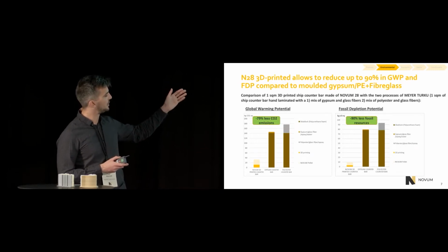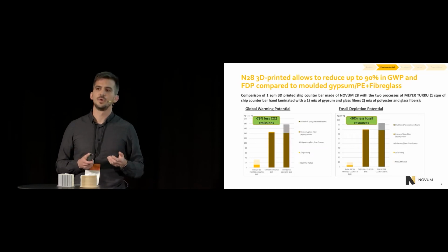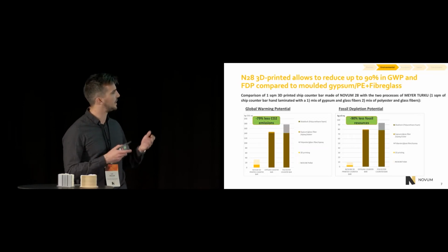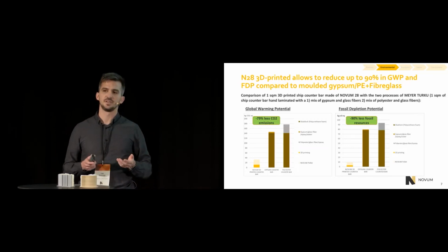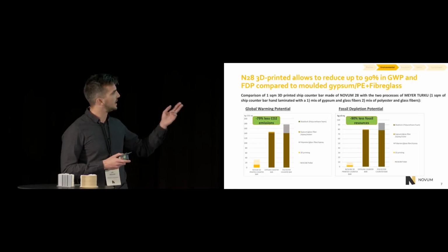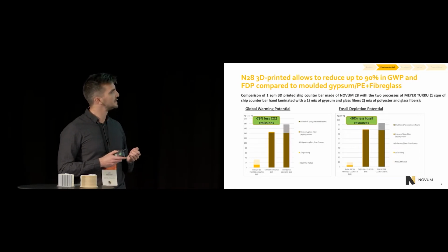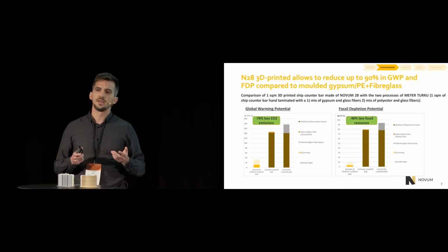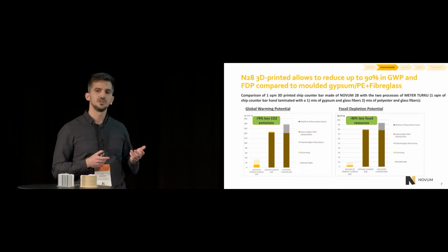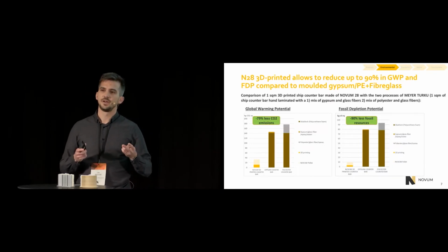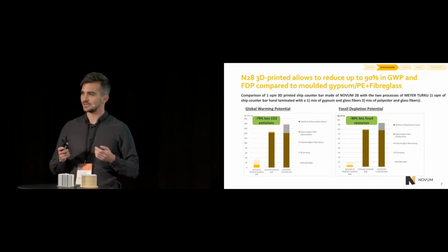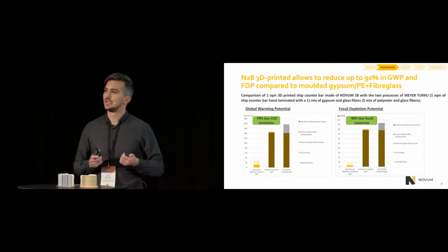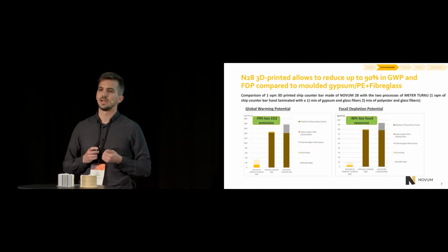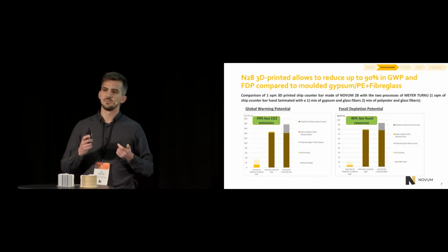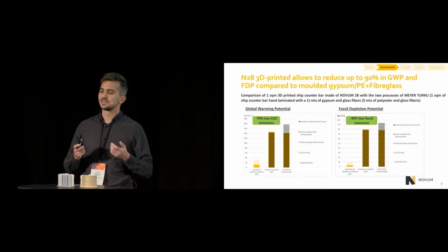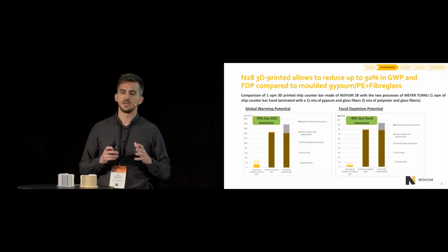So the first one on the left is our process, the NOVUM 28 material formulation plus the 3D printing of Brinter. And then for the second and third processes, they're developed by Meyer Turku using hand lamination with 2 different mixes of material. So the first one in the middle is a mix of gypsum and glass fiber, and the second one is a mix of polyester and glass fiber. So they're both using hand lamination.